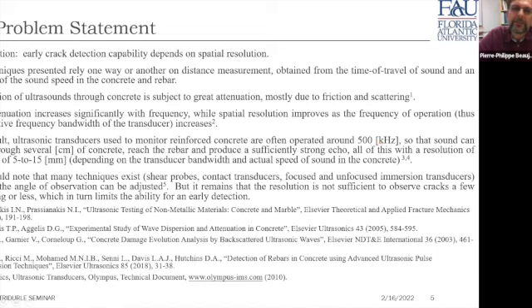So that the sound can travel, for example, at 500 kilohertz through several centimeters of concrete, reach the rebar, and produce a sufficiently strong echo. All of this with a resolution of the order of 5 to 15 millimeters, depending on the transducer frequency bandwidth and the actual speed of sound in the concrete.